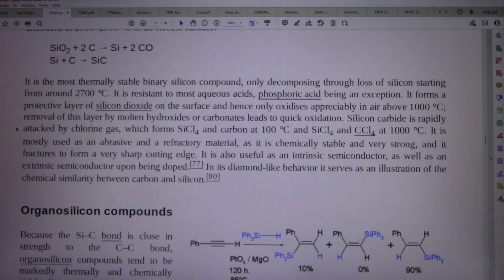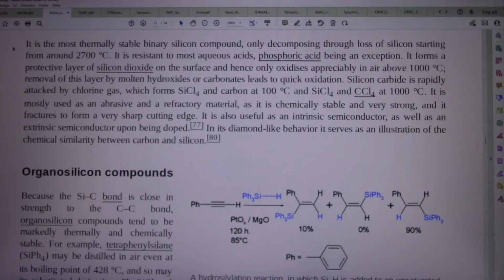It is the most thermally stable binary silicon compound, only decomposing through loss of silicon starting from around 2700 degrees Celsius. It is resistant to most aqueous acids, phosphoric acid being an exception. It forms a protective layer of silicon dioxide on the surface and hence only oxidizes appreciably in air above 1000 degrees C. Removal of this layer by molten hydroxides or carbonates leads to quick oxidation. Silicon carbide is rapidly attacked by chlorine gas, which forms SiCl4 and carbon at 100 degrees Celsius and SiCl4 and CCl4 at 1000 degrees Celsius.